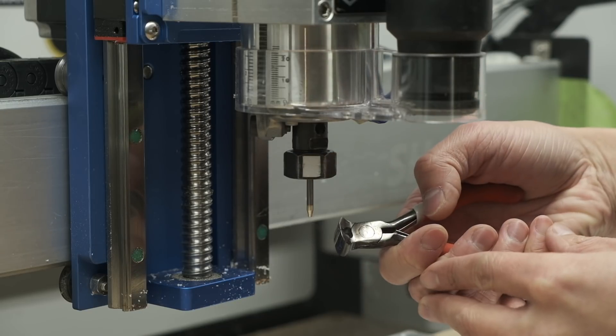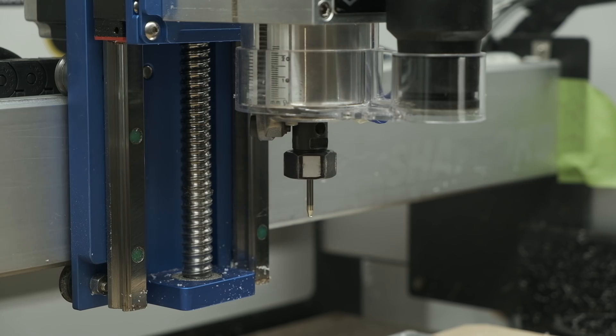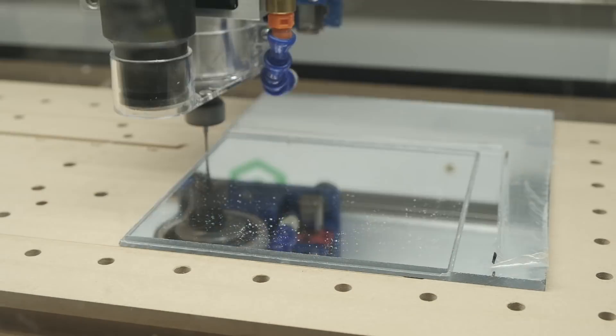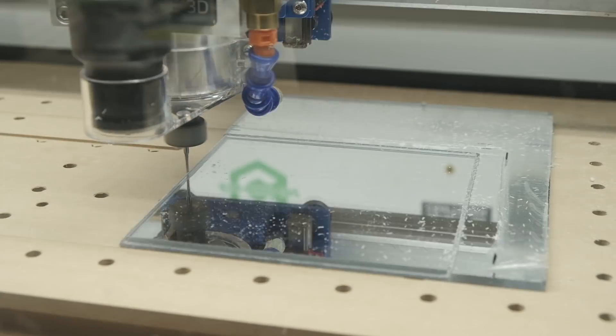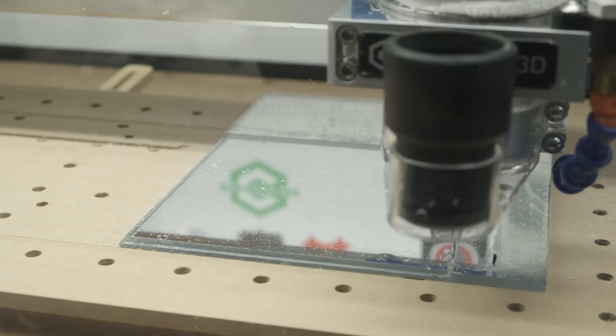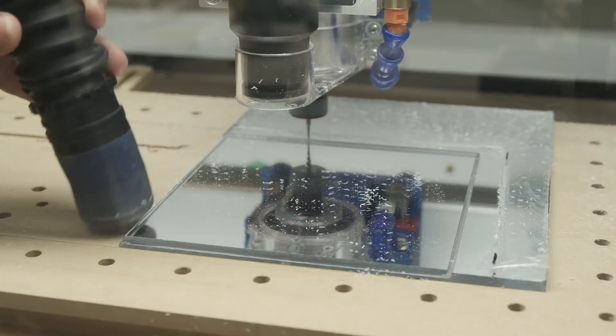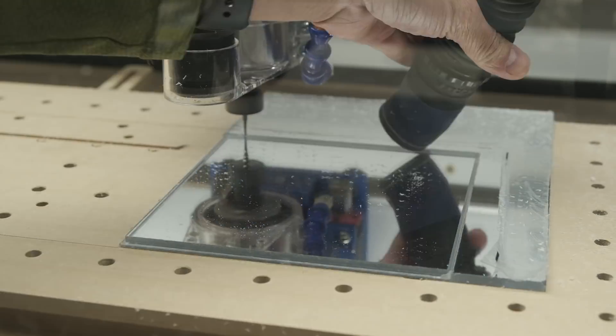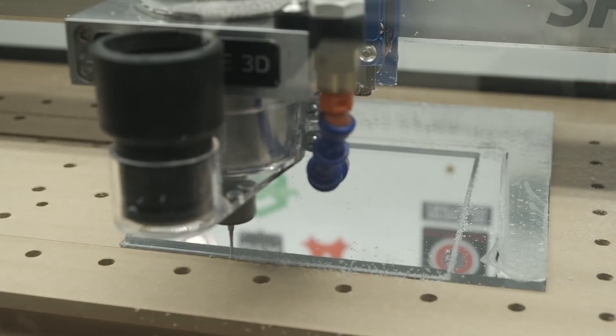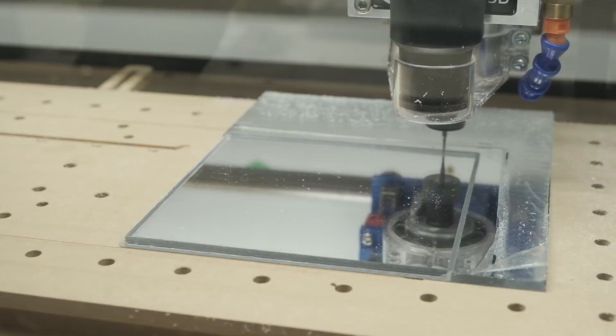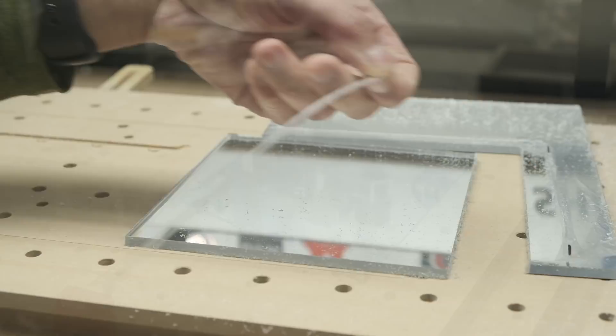In hindsight, using a lighter or heat gun might have helped the acrylic to release more easily, but I was in more of a brute force mood that night. With this end mill a lost cause, I had to abort the execution of the program so I could install a new tool. This time I dropped the RPMs all the way down to 10,000. Since I had cut more than halfway through the acrylic, I could just run the toolpath from my polycarbonate mirror since that was the same shape, just thinner. That would save me a couple minutes of air cutting. And finally, I had the acrylic mirror cut out.